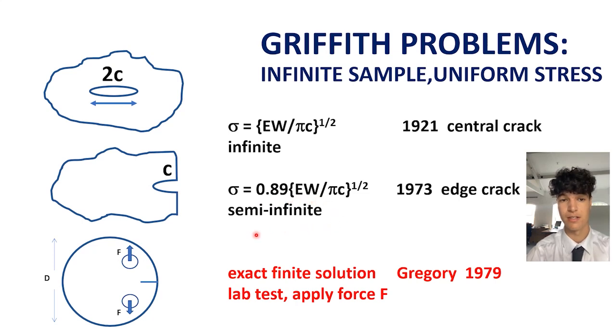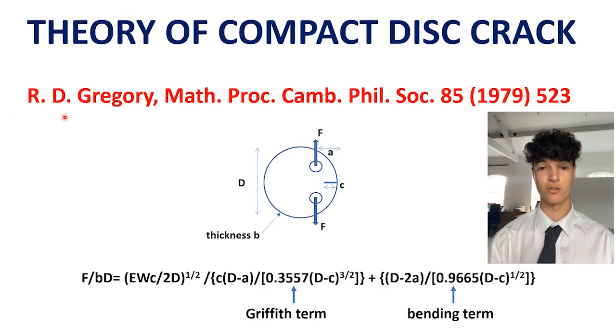Then 6 years later, Gregory produced his exact equation for a lab crack test on discs. Ronald Douglas Gregory was a mathematician at Manchester University who used the energy conservation principle to get this unique equation, published in the Cambridge Philosophical Society in 1979. This is a Griffith-like term, while this is a bending term. The nominal strength is F over BD, and I've been calculating the strength for perspex discs, which are known to crack very controllably, so we can test this experimentally later.